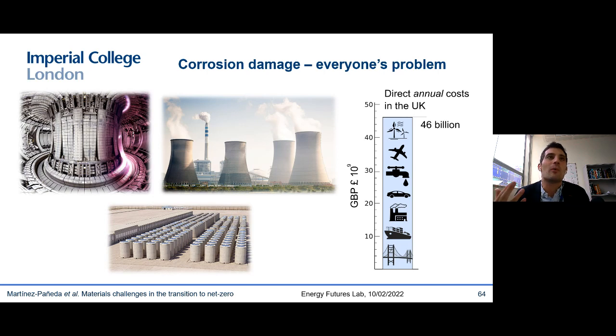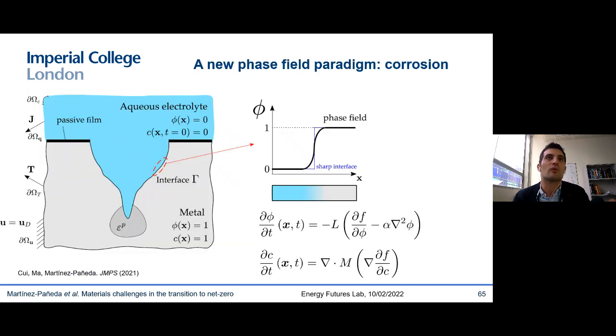But basically what I want to say here is that corrosion has always been thought of as too complex a problem to predict using computers. However, I do think that there's an opportunity now to achieve this elusive goal. There are two issues that we need to tackle: the multiphysics nature of the problem, so it crosses multiple disciplines, and also predicting the evolution of interfaces, so predicting the evolution of the corrosion front. And we have seen before that computers are powerful enough these days to model complex coupled physical phenomena. And we have also seen before that there's a new paradigm that can be exploited to easily track interfaces. What I'm talking about here is, again, this phase field paradigm that I mentioned before.